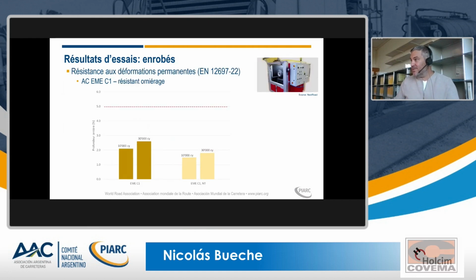More interesting, the rutting tests. What we do in Switzerland, this is a French rutting tester. So we do slabs that will be tested, as you can see in the picture on the right-hand side. And we have a limit value of 5% rutting, so it's proportional to the slab thickness. Slab thickness is 10 centimeters, and the limit value is 5%.